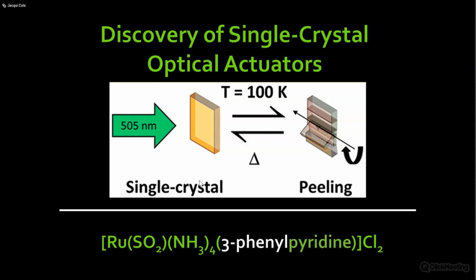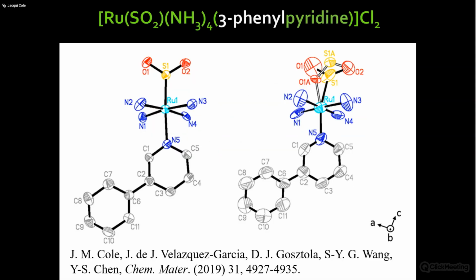And what happens, I'll tell you before I show you, is we fire the same sort of green light at the single crystal. We keep it cool, same temperature, 100 Kelvin. And what happens is the crystal literally peels up. And I really mean macroscopically. You can see this in an optical microscope. It's literally the crystal itself peeling. We thought it was just going to explode or something, but it does something even more strange than that, as